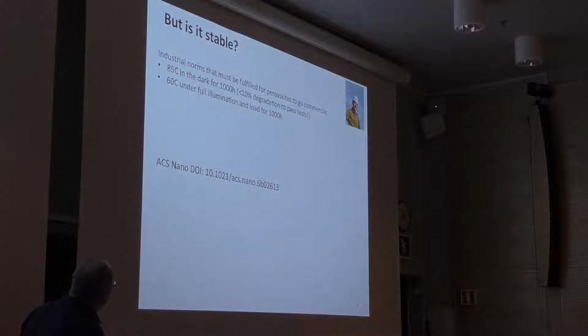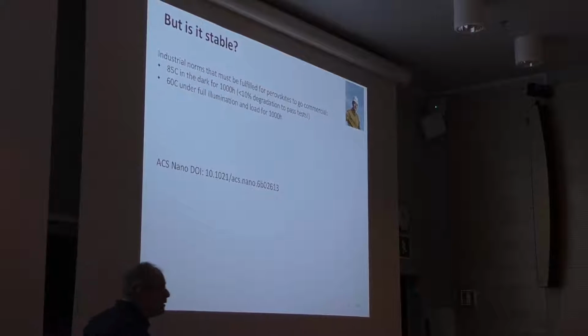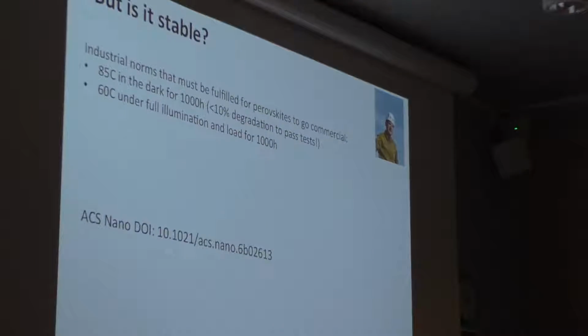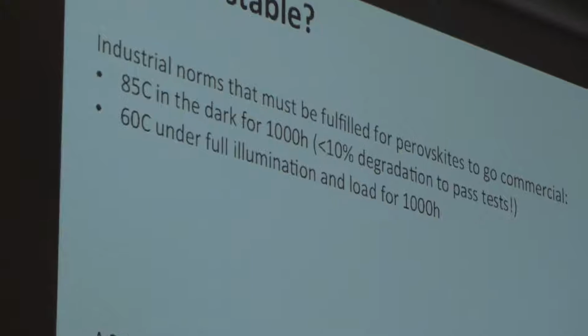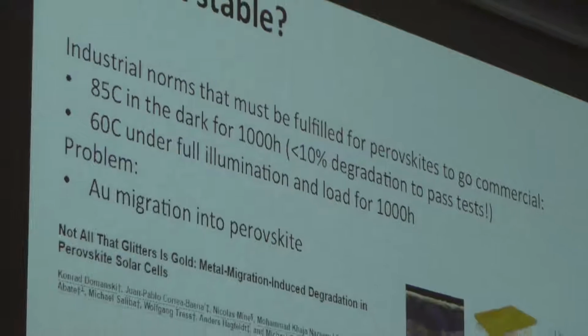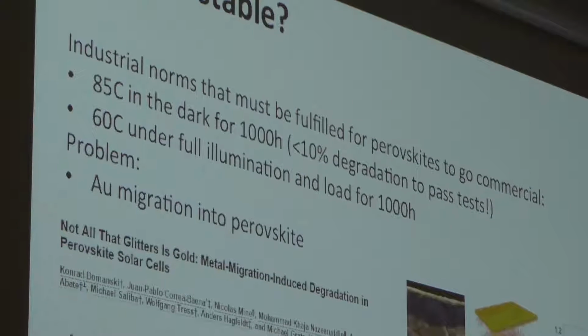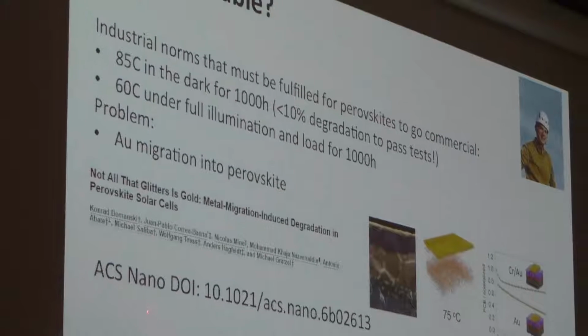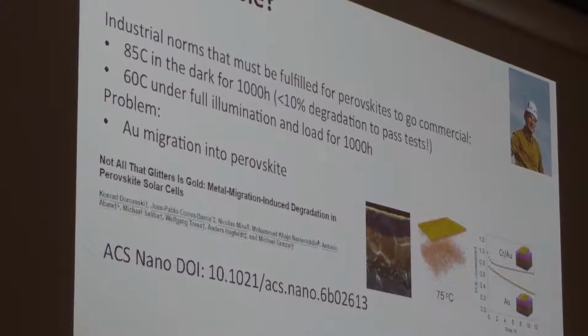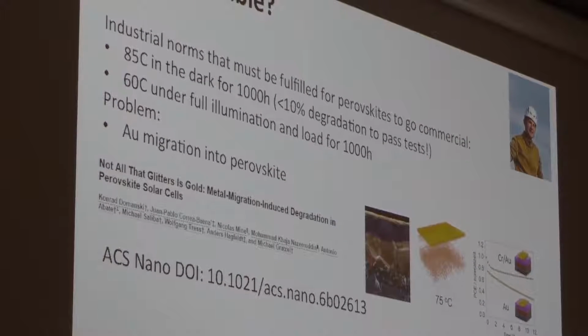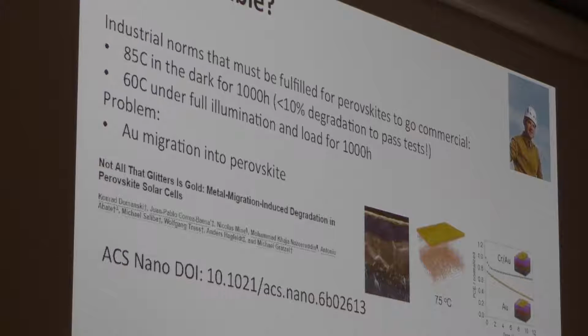So I'm coming to the end. What about stability at high temperature? That's the last question. We had some insight also published this year that a problem at high temperature, because we use Spiro and we use gold as contact, and we tested them at 85 degrees Celsius and they were completely degrading very quickly. So it's no stability with that, and we thought it had to do with the perovskite film is unstable.